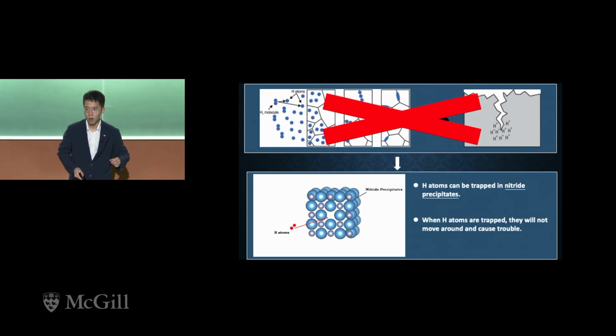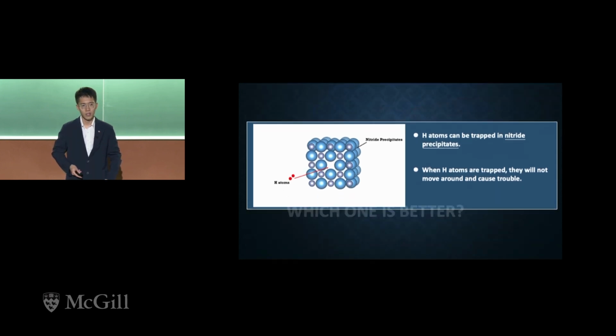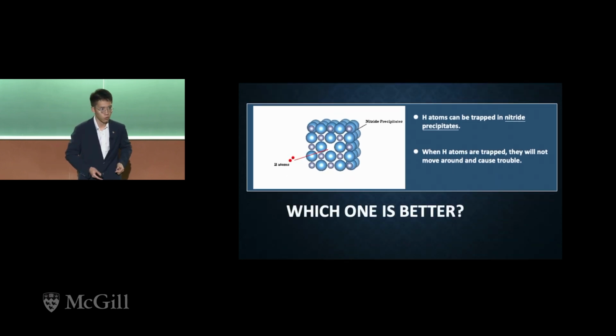My research aims to combat this issue by using nitride precipitates, which are tiny particles in steels that can trap those diffusible hydrogen atoms, preventing them from causing damage. However, some nitrides are better suited for trapping hydrogen atoms, while others may let them through. My goal is to identify the most effective nitride precipitates to enhance steel's resistance to hydrogen embrittlement.